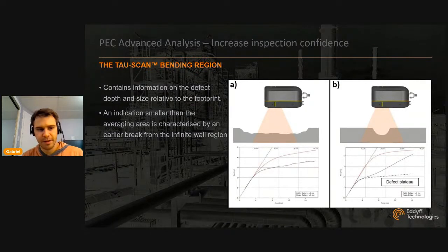The bending region of the Tau scan, so that's the middle part of our Tau scan, contains information on the defect depth as well as its size. So if you've got a smaller indication like this one here, you'll see the signal curve in black leave the calibration curve earlier on. And that's because in that Tau scan, there is information from two different wall thicknesses. You get a plateau region that's defined by the defect. So that's the characteristic decay time of the defect. And then you've got another plateau that would come up later that corresponds to the surrounding nominal wall thickness. Whereas if you're scanning an area of generalized wall loss larger than the probe averaging area, the bending point is going to be later in time. So the curve is going to leave later and end with just one plateau.